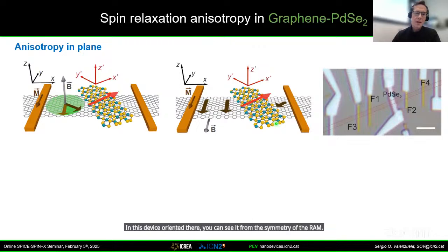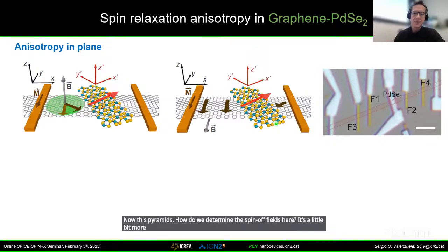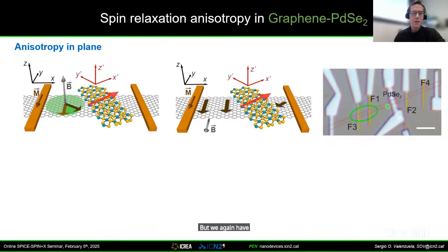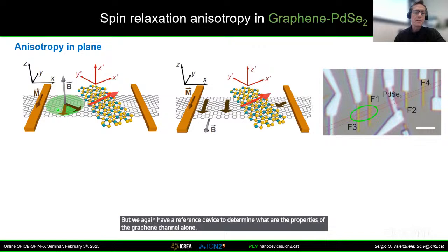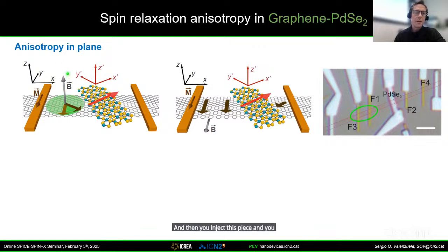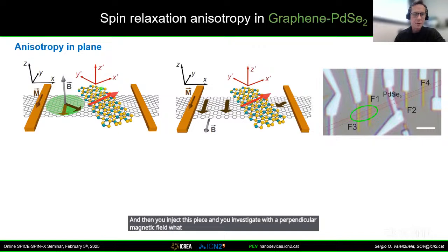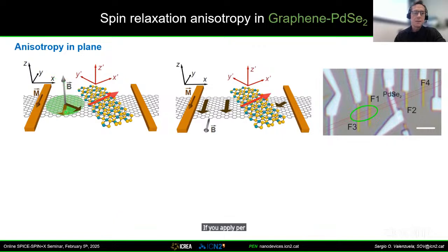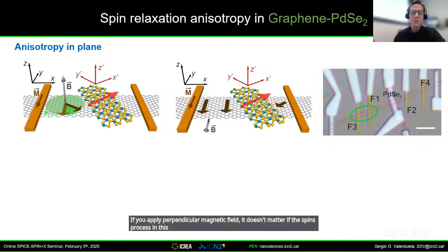Now, the experiments. How do we determine the spin orbit fields here? It's a little bit more complicated. We had to make the spins precess in different ways. But we again have a reference device to determine the properties of the graphene channel alone. And then you inject the spins and you investigate with a perpendicular magnetic field what happens in this part. Forget about the palladium diselenide now. If you apply a perpendicular magnetic field, it doesn't matter if the spins precess in this way or that way. It should give you the same result because these 2 ferromagnets are parallel to each other.